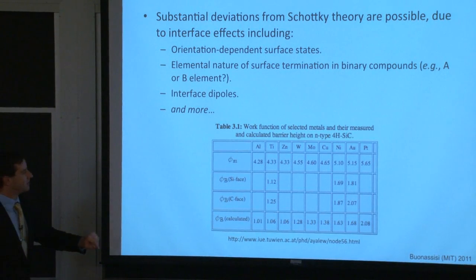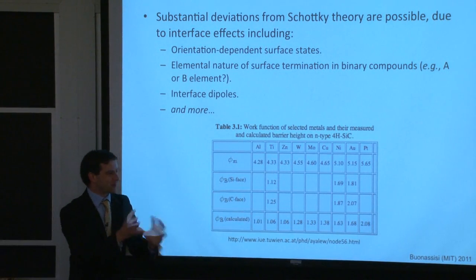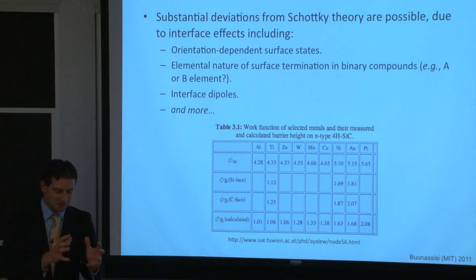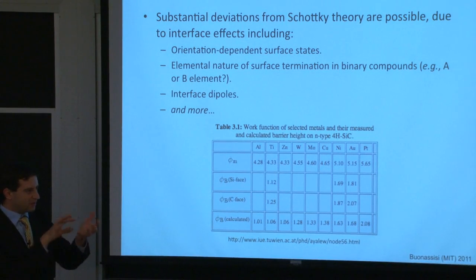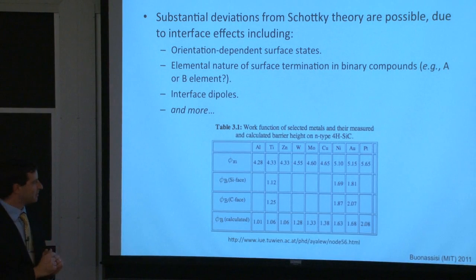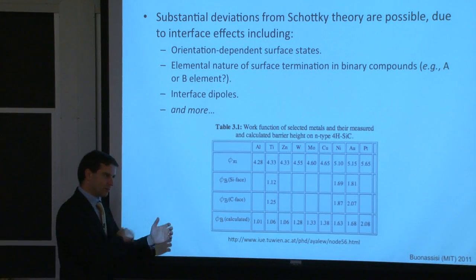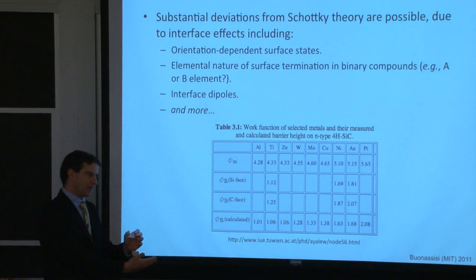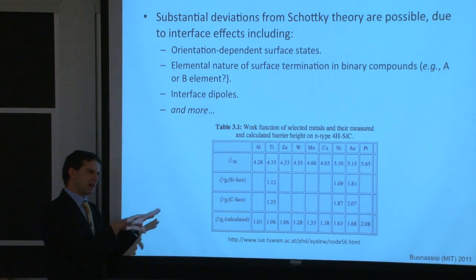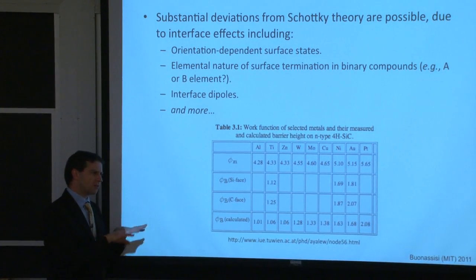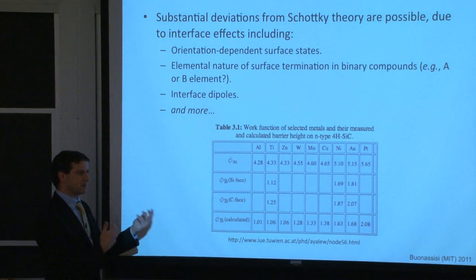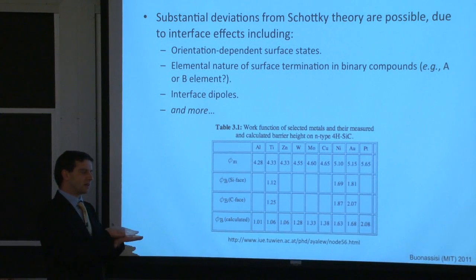Orientation dependence means, gee, if I have an anisotropic crystal, meaning a crystal that looks a little bit different if I rotate it around in different orientations. If I make cuts in different directions, exposing different planes, there are going to be a different density of atoms in that plane. There's going to be a different charge distribution in that plane, and hence I would expect there to be some different interaction between the semiconductor and the metal at that interface.